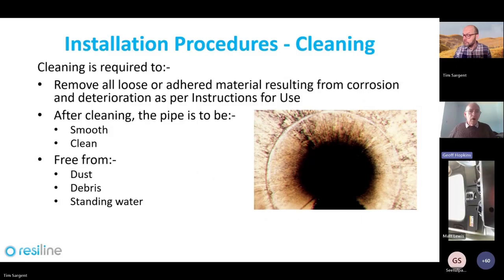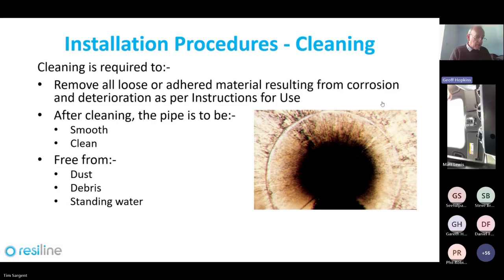So, cleaning is required to remove all loose or adhered material resulting from the corrosion process, as per the instructions for use issued by the material manufacturer for the product, and the water industry specification states that after cleaning, the pipe is to be smooth, clean, and free from dust, debris, and standing water. As I say, they're taken from the UK industry spec, which is Water Industry Spec 40201.